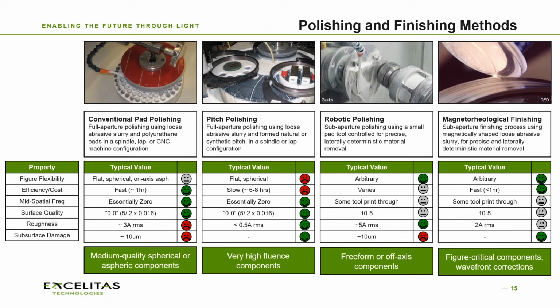When the surface form gets a little bit more demanding, farther away from spherical or flat surfaces, that's where we start to get into some of the more deterministic and flexible processes like robotic or computer-controlled polishing or magnetorheological finishing, MRF. In the first case, robotic polishing is actually a polishing process, and therefore can turn a ground surface into a high-quality specular polished surface. MRF is a finishing process, which means it doesn't technically polish the surface, but it can correct small errors in the surface. So these things can be used as complements to one another,